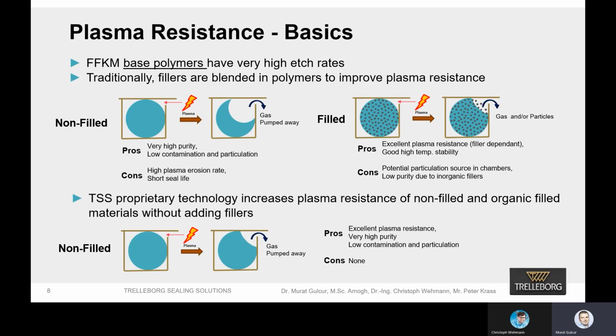So the advantages of this non-filled material is obviously, because of the number of ingredients in the formulation, just curative and the polymer, the purity is quite high. Therefore, the contamination is low, the chance of particulation is extremely low. However, the disadvantage of this system is having very high plasma erosion rate, and therefore having short seal life, and being a little bit more expensive than other elastomer choices.